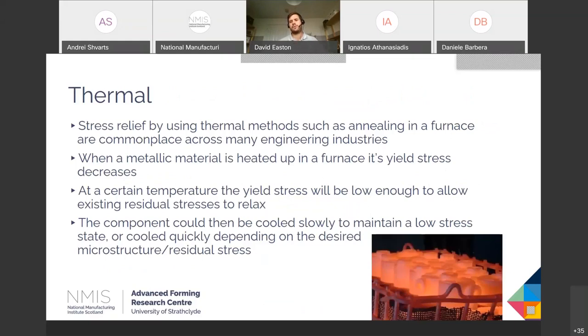So thermal is probably the most widely applied stress relief technology. It typically involves putting a part in a furnace, and we increase the temperature until the stress is relieved. This is achieved because as metals are heated up, their yield stress drops. Eventually we reach a level where the yield stress matches the residual stress of the part and the stresses are relaxed. We can then decide how we want to cool the part, whether slowly to maintain a low stress condition, or quickly if we need a certain microstructure or residual stress. But that's the basics of thermal stress relief.